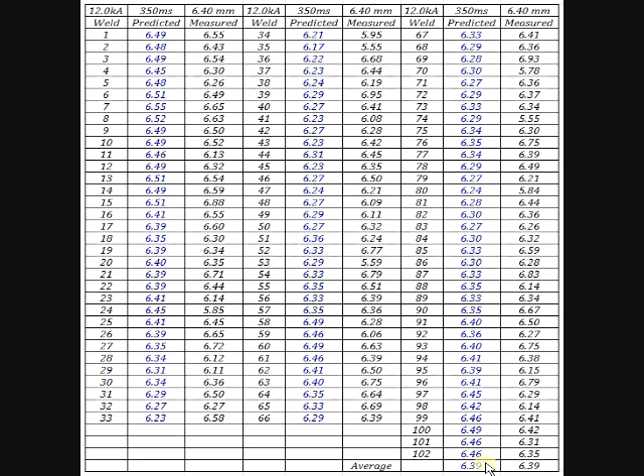The predicted average is 6.39 millimeter, and the measured nugget diameter is 6.39 as well. Compare that with 6.40, what we wanted to weld with the 6.40 millimeter cap. This is extremely close.